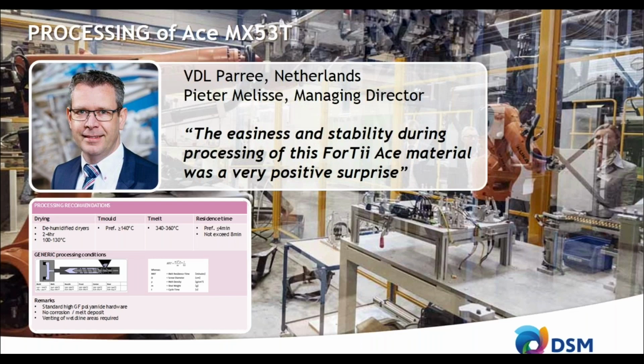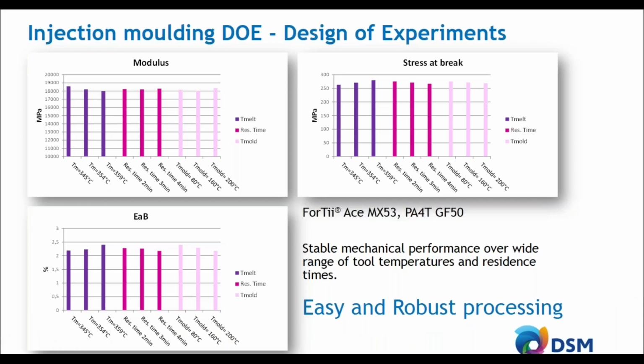But of course, I can imagine that you also would like to see some proof. What we typically do is we do a lot of design of experiments. We do extensive testing of the materials on different machines under different settings to ensure that you can have an easy and robust processing. This is a typical example, a part of the DOE that we have been doing for ForTii Ace MX53, so the PA4T with 50% of glass. We made a variation, for example, in the melt temperature, in the residence time, and also in the mold temperature. And then we assess the modulus, stress at break, and for example, the elongation at break.